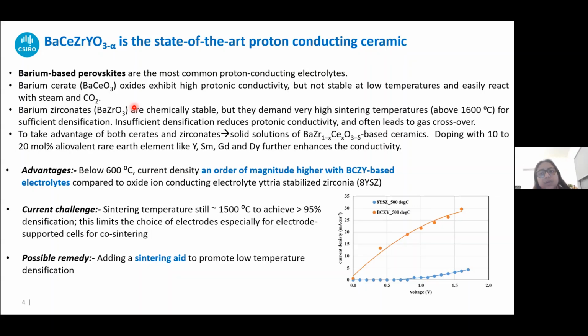And then it was found that doping with maybe 10 to 20 mole percent of a rare earth element like yttrium or samarium or gadolinium further enhances the conductivity. However, the most common material is barium cerium zirconium yttrium oxide. Now, as I already mentioned, the advantage is that it has a higher conductivity in the intermediate temperature range.